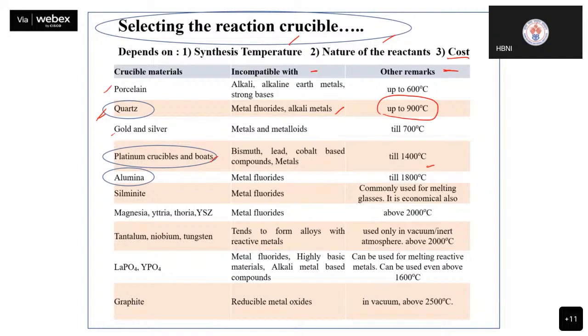All right. Alumina. Alumina is what we use regularly, day in and day out. You can use them up to 1800. Beyond that, very, very rarely only you go for any synthesis. But the only thing is you cannot use them with fluoride. You can use them for all the other things up to 1800, but not fluoride. Okay, and if you want to go to super high temperature, for example above 2000, then these are the materials of choice for you: magnesia, yttria, thoria, YSZ, all of them have got melting point beyond 2400.